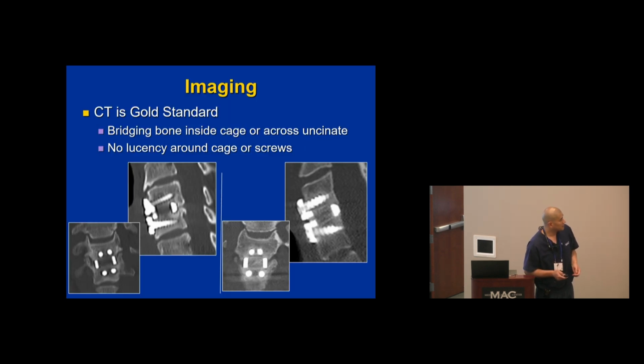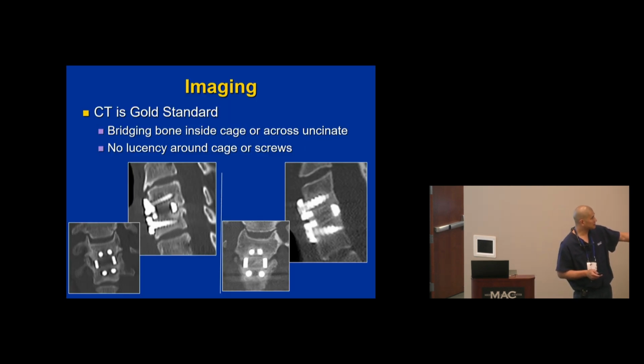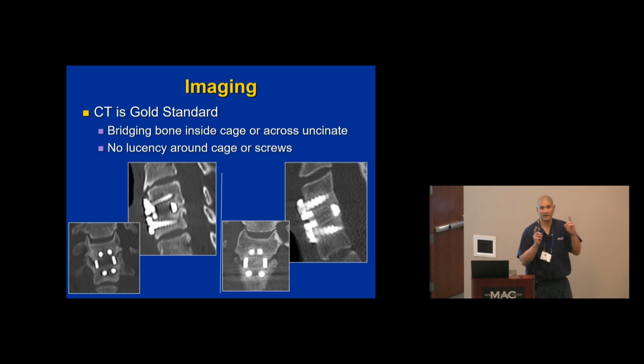So these are both younger patients, and you can clearly see on the left, there's no bone bridging across. There's a little bit of haloing around the metal. And this is another patient where you do see bone possibly on-growing onto the metal. You do see bone growing across. And frankly, when I'm looking at a non-union, I specifically look at the uncinate, because if you go really lateral on your approach, more often than not, you'll see the uncinate fill in before you see the interbody fill in. So I'll use that uncinate sign as something that documents fusion.